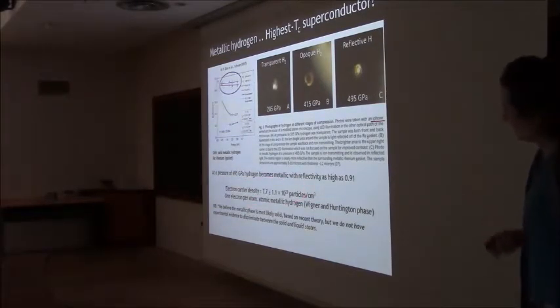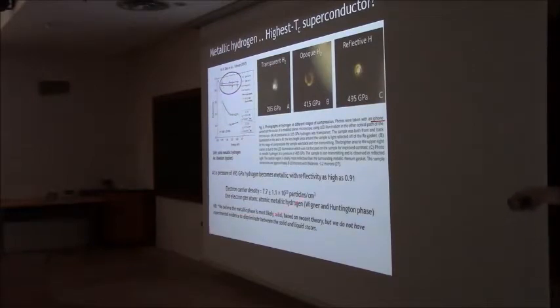So they also evaluated the carrier density, which is as usual, so it's not a dilute superconductor, and they know that they have 1 electron per atom, which is as expected for the so-called Wigner and Huntington phase, so it's atomic, metallic hydrogen.